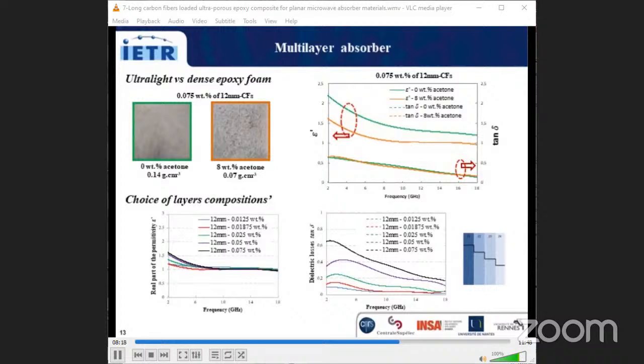On the other hand, we observe that the losses increase when the concentration of carbon fiber increases. We notice also that the samples show a gradient of losses, which allows us to realize a multi-layer with an impedance gradient.